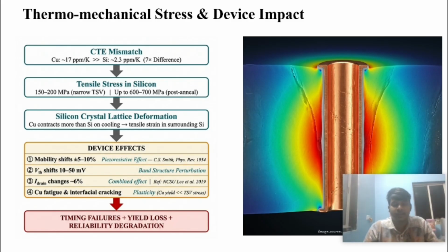So when copper shrinks from 250 to 300 degrees Celsius to room temperature, this will lead to residual tensile stresses of up to 700 megapascals at the edges of the silicon wafer. This will lead to silicon crystal lattice deformations, and this will affect mobility shifts, threshold voltage, and drain currents. Also, this will lead to copper fatigue and interfacial cracking.